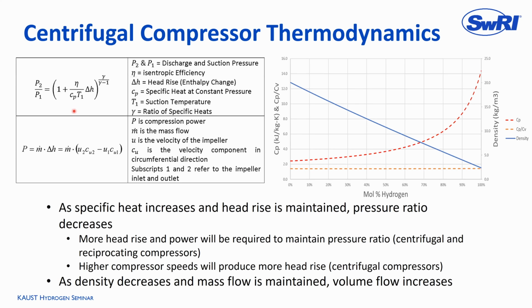So what does that mean in terms of compression? This is the equation, regardless of the type of compressor, of how you get pressure ratio through work. So on the left-hand side is pressure ratio. It's a function of the compression efficiency, the specific heat in the denominator, the work or the head rise shown here, and the specific heat ratio is here. So when you change from natural gas to hydrogen, the specific heat ratio is about the same. What really changes is the specific heat goes way up. And so what that means is that if you want to get the same pressure ratio as the specific heat increases by an order of magnitude, you've really got to do a lot more work with enthalpy rise to get the same amount of pressure rise.